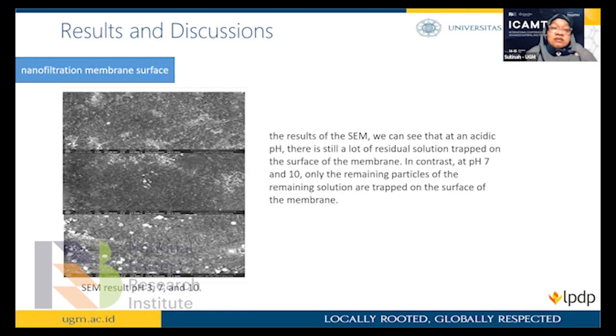And then the nanofiltration membrane surface was examined using SEM at pH 3, 7, and 10. From the SEM results, we can see that at acidic pH a lot of residual solution is trapped on the surface of the membrane. It is in contrast with pH 7 and 10, where only a few particles of the remaining solution are trapped on the surface of the membrane.